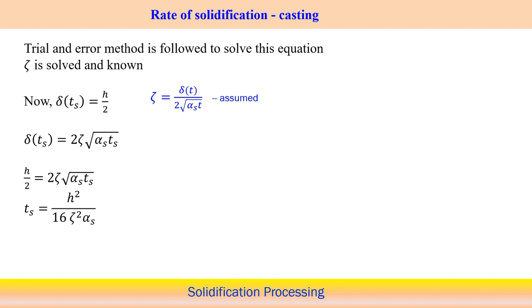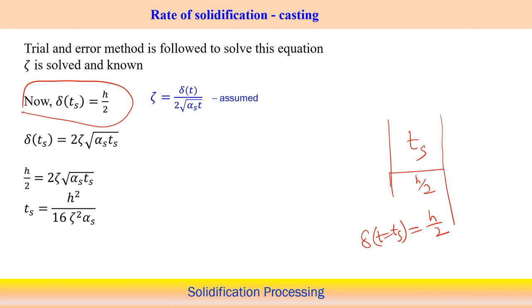Now we have seen that the solidification from the mold is basically h by 2 distance at time ts, and that is why we have written the solidification thickness delta at time t equal to ts should be equal to h by 2. That we can use here also, and in this case of course we assume zeta equal to delta t by twice root of alpha s into t. That was the assumption, that zeta equals this value. Now from here you can see that at time t equal to ts, delta ts equals twice zeta into square root of alpha s into ts.